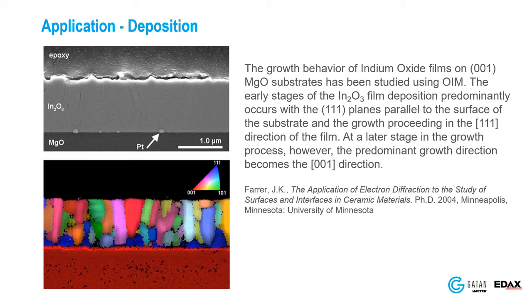Question: Can EBSD be performed on TEM samples? Yes — that is what I referenced as TKD, transmission Kikuchi diffraction. We use a very different arrangement, tilting the other direction, maybe only to 30 degrees. We can use the EBSD detector to image the material, though the signal all comes from the bottom of the sample rather than the top. Results will be affected by the thickness. TKD helps improve spatial resolution as well.